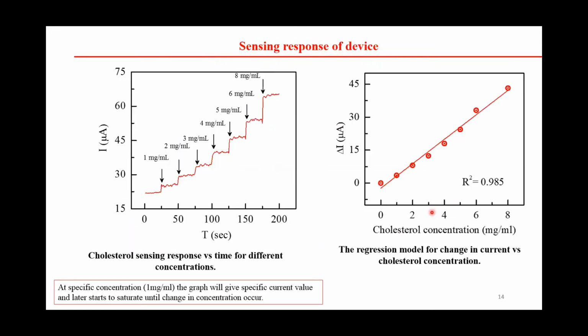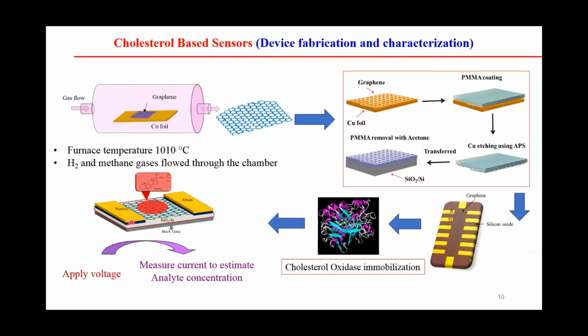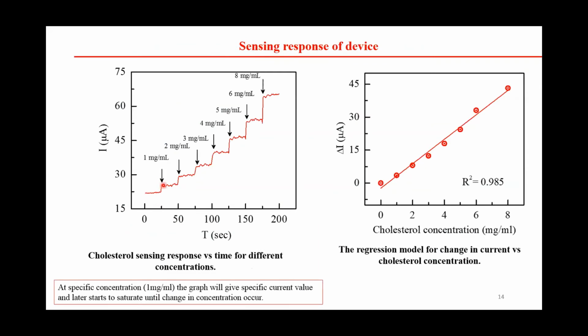We can also do this sensing directly. Suppose a normal sensing device. We have a concentration of the cholesterol, and we apply the potential and measure the current, and there will be one value of the current for the reference case. When we increase the concentration, the current should increase or decrease. In this case, our current is increasing when we increase the concentration from 1 mg per ml to 2 mg per ml. So we can make it more precise if we decrease the concentration to 1 mg or less than 1 mg. We can make a more precise detection element.